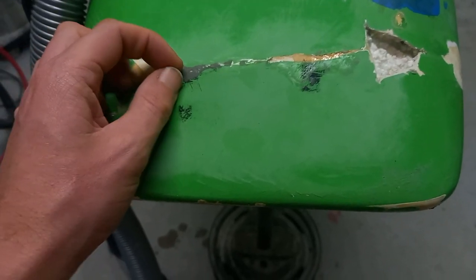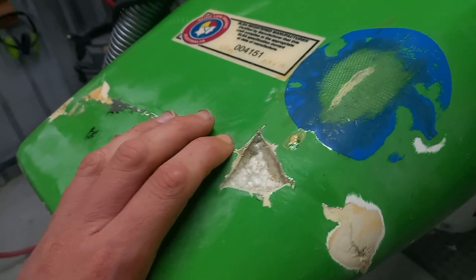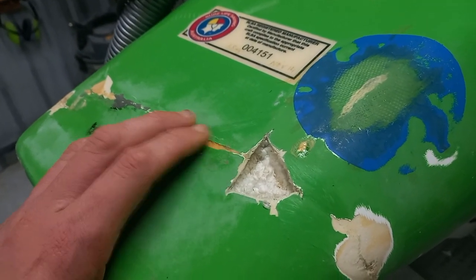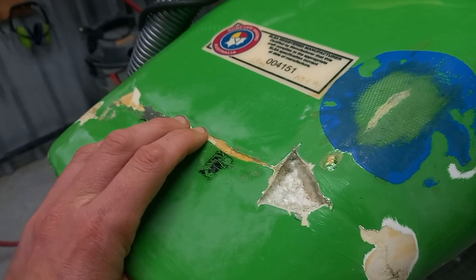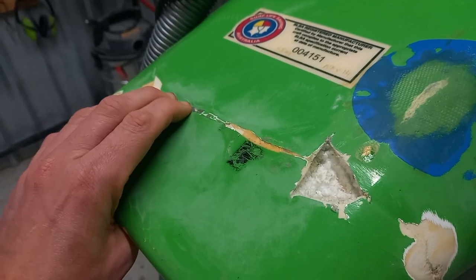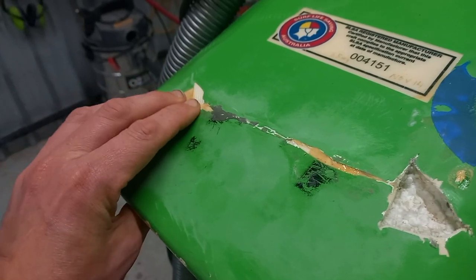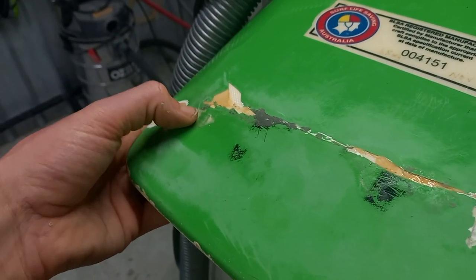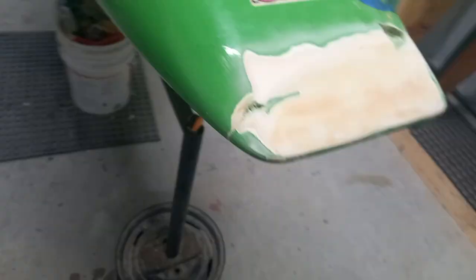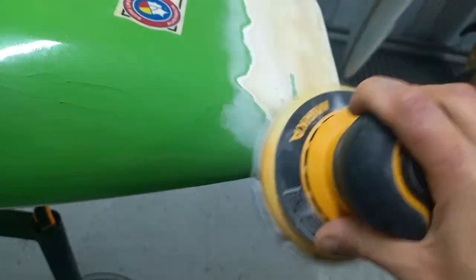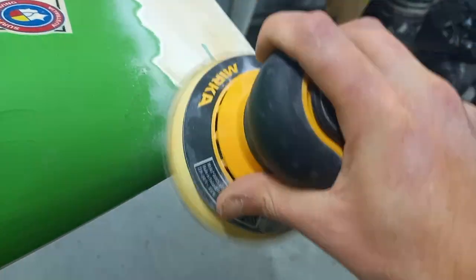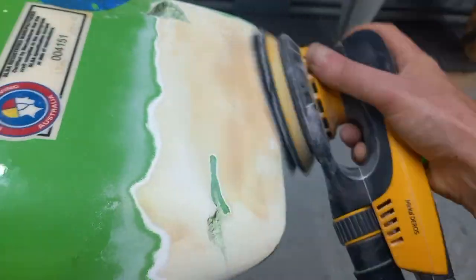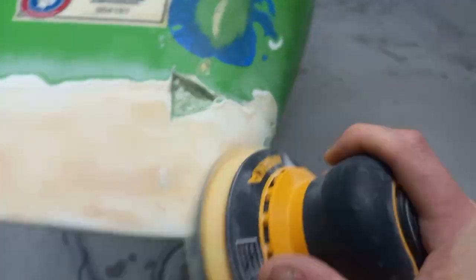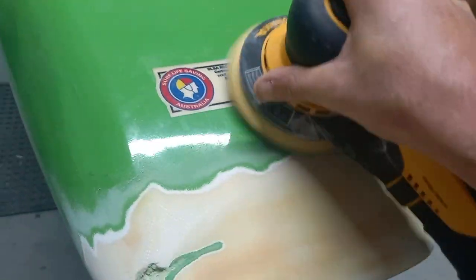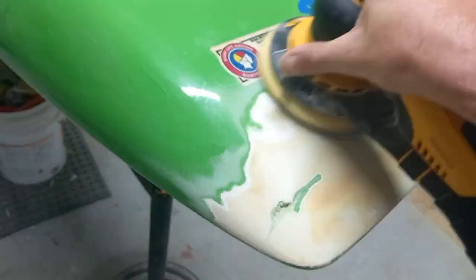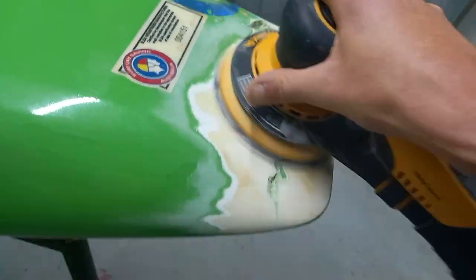So we're going to focus on the tail of this board. You can see between each gouge down to the foam, there's actually a crease, and you can see that glass moving, so it is delamed. So we're going to weaken the glass up with some 80 grit sandpaper as much as we can and really see what's going on under there. So 80 grit is pretty coarse to start a board off with, but because we want to thin the glass out to make cutting easier, we want to remove the paint so we can actually see what's going on, and ultimately there's no structural integrity to this fiberglass at all. 80 grit's just going to get our sanding done quicker.